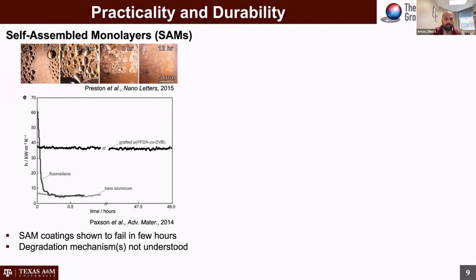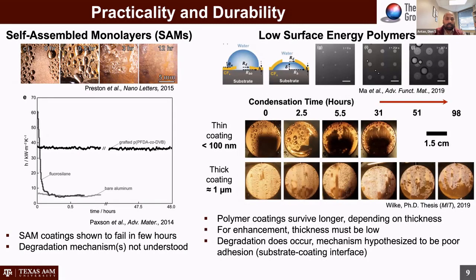Now, these coatings that we have for dropwise condensation are typically either self-assembled monolayers or they are polymers. In the case of the self-assembled monolayers, which are very widely used in our community to demonstrate dropwise condensation, these coatings fail fairly quickly. The literature says within a few hours, but if you look at the data, it's always within about 30 minutes to less than an hour that these typically fluorosilane SAMs fail. And while the degradation mechanisms have been proposed to be some type of oxidation, there's no clear indication of what that is.